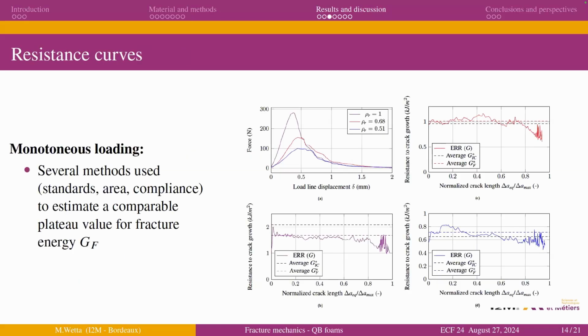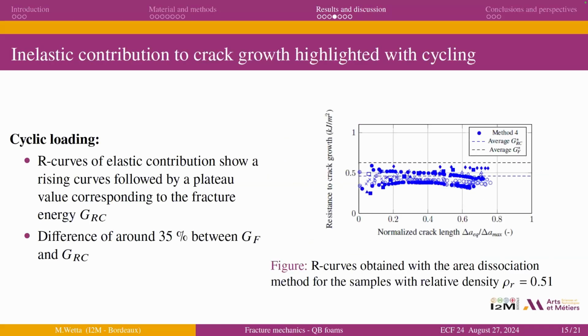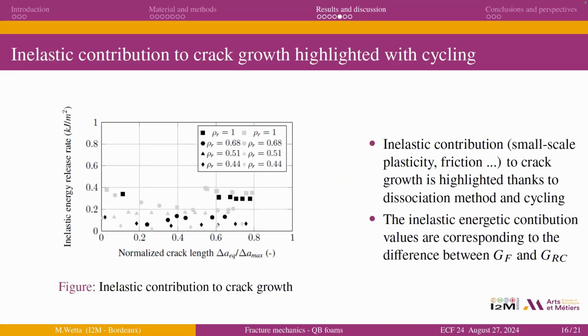The next result concerns the monotonous loading. We have compared several classical methods, the standards, with the maximum load, the area, with the global area under the monotonous loading, so the force displacement curve, and the compliance. We have observed that whatever the density, we have a comparable value of the fracture energy, GF. And when we compare with the cyclic loading, where we construct the resistance curve with the elastic part of the energy, we can observe that we can reach a plateau value, which is quite different from the fracture energy measured before with the monotonous one. We have a difference of approximately 30%. And this difference is directly explained by the inelastic part of the energy.